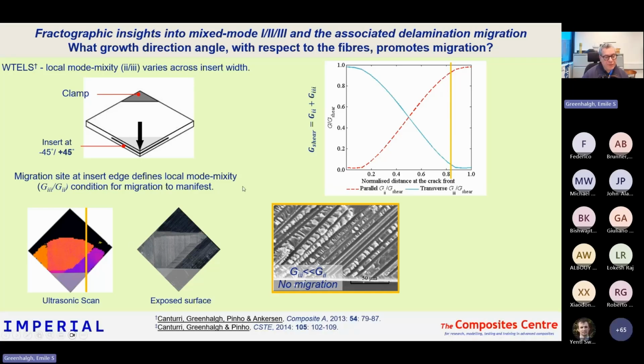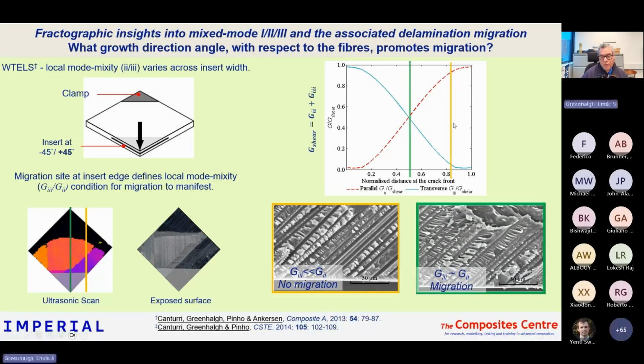But as we move towards the left here, we start to find that the mode mixity now is pretty much equal, the mode 2 and 3 components, and we start to see migration occurring. You can see the cusps are twisted with respect to the fiber direction. And that actually allowed us to come up with, for this particular material system, what the critical conditions are for migration to occur. So that was my summary of what we've done from a fractographic perspective to try and understand mixed mode 2, 3 and the migration process that occurs.